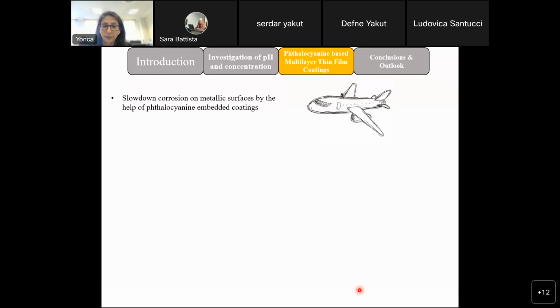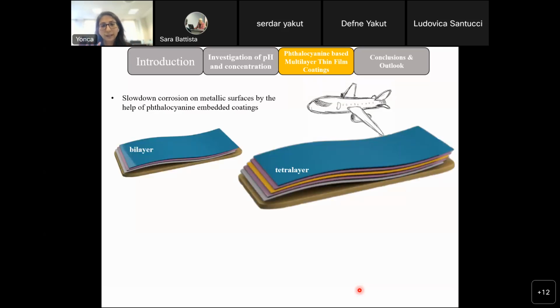So to do that, I've studied two different architectures, a bilayer structure and a tetralayer structure. What I mean is the bilayer structure is exactly the same as what you have seen in the previous slides. And in the tetralayer structures, I have more polyelectrolyte layers and phthalocyanine layers, so more polyelectrolytes and then a single layer of phthalocyanine. So in the tetralayer structures, we have less contribution of the phthalocyanine.